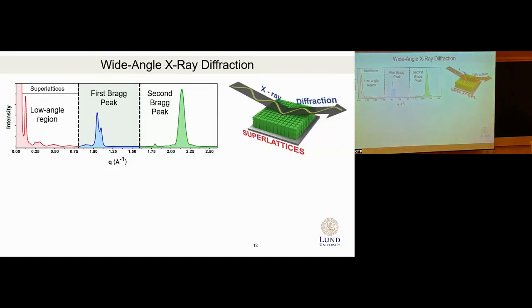Next, we recorded wide-angle X-ray diffraction measurement. So it's a very simple experiment in a typical diffractometer in chemistry labs. You put the sample, there's an incident beam, diffracted beam, and you scan it as a function of angle using a detector. So what we saw is the following.